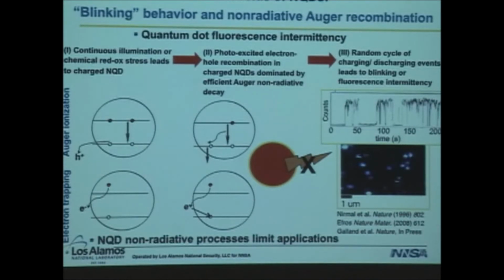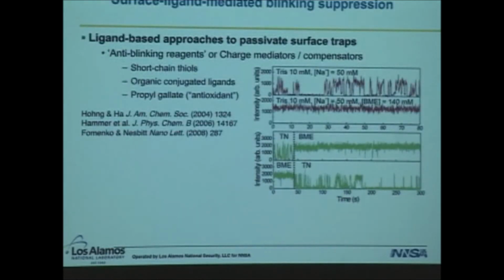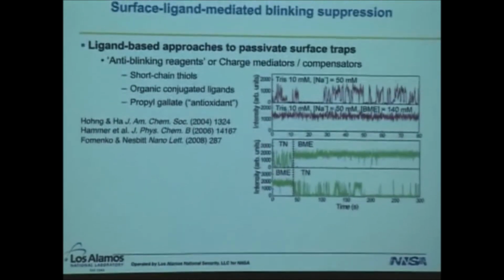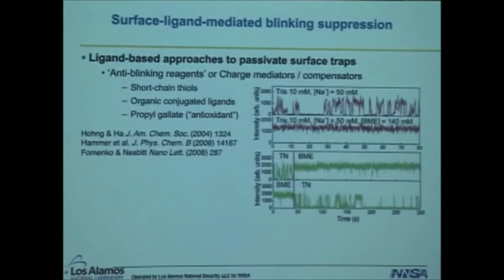And so anyway, in general, non-radiative processes limit applications, and so many folks over a number of years have attempted to suppress blinking behavior. For quite a few years, the primary focus was on using organic ligands to suppress blinking, and these were so-called anti-blinking reagents. They were typically reducing agents that would serve to passivate surface trap states, for example, and if you applied these in a correct fashion, you could indeed suppress blinking, as shown here on the right. This bottom trace and this top green trace are examples of non-blinking behavior.